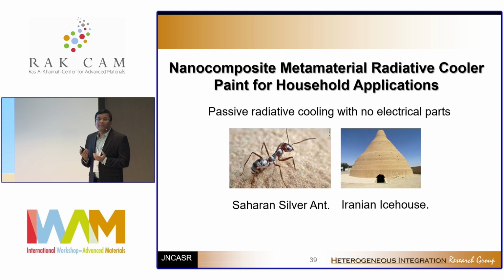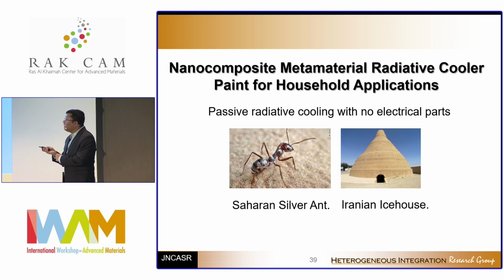Because in high summer, pretty much everything heats up. And when it heats up, it makes it very, very hot to even touch it. It turns out that nature has already figured out how to radiatively, passively cool, because there is a Saharan silver ant, one of the smartest creatures on the planet. It survives in the Sahara Desert at 50, 60 degrees centigrade temperature, because you see there is a silverish coating on its surface, which basically helps it to reflect the entire solar spectra. At the same time, it has certain fibers in its body, which basically emit in the infrared or atmospheric transmission window. So this is one of the inspirations from nature we used to design this passive radiative cooling.